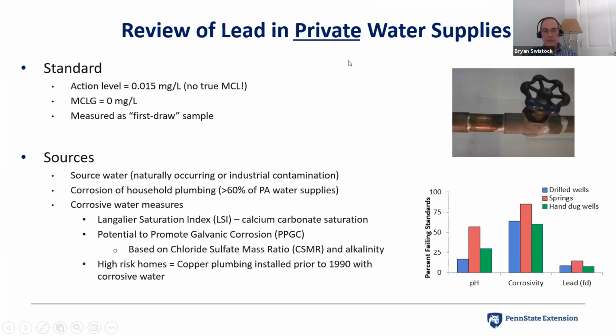The sources of lead, as Reem mentioned, there are occasional cases of source water contamination. Even naturally occurring lead can happen, but those are typically pretty rare, and I'll show you some data on that. The typical source is corrosion of household plumbing, and in Pennsylvania, corrosive water is the most common water quality issue that we run into. More than 60% of our wells and springs have corrosive water. The graphic down on the bottom right there shows that it even varies quite a bit by water supply type, where springs tend to be the worst because they have the most corrosive water. They tend to have higher lead levels. They also tend to be associated with older homes too. So springs are typically our worst case scenario, where we have the most corrosive water under the conditions where lead is present. Drilled wells are usually a little bit less of an issue.